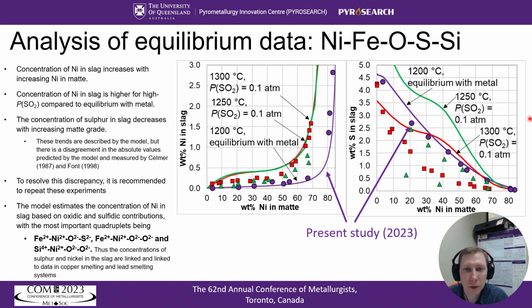The concentration of sulfur in slag is important because of the sulfidic mechanism of solubility of nickel in slag. In the modified quasi-chemical model, this mechanism is realized through the introduction of nickel-containing quadruplets. The most important one is iron, nickel, oxygen, sulfur. There is a discrepancy in the model predictions and literature data for the high PSO2 conditions. We recently reproduced those experiments, and even though not shown here, the preliminary results confirm the model predictions for nickel and sulfur in slag for the high PSO2.